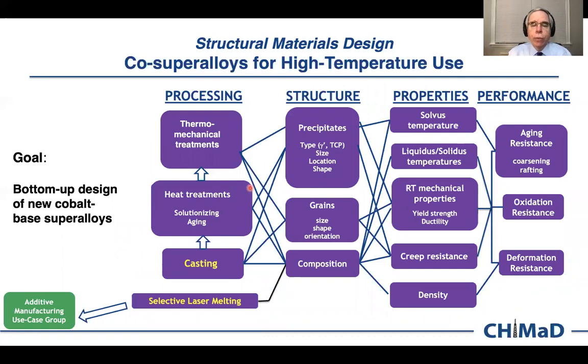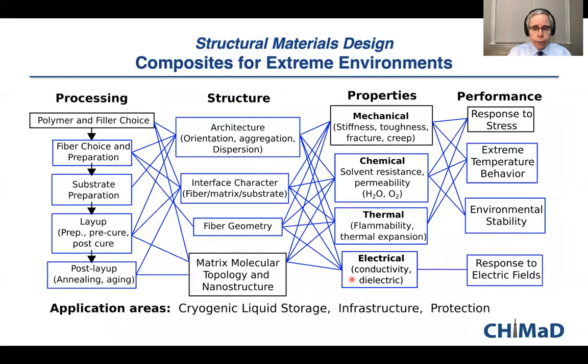And every use case group has a design chart that looks something like this, where processing, structure, properties and performance are linked together, and what goes into these boxes is unique to every use case group. And so this is the cobalt superalloys group, and so they're worried about casting or selective laser melting. This is an additive manufacturing example where we take the results and we interact with the additive manufacturing use case group I just showed you before. But you use the processing and the casting, and the processing leads to the precipitates of given sizes, the mechanical properties, and that gives rise to the performance you need for a particular application, like the oxidation resistance, deformation or creep resistance, and the aging resistance of the precipitates, or the coarsening resistance.